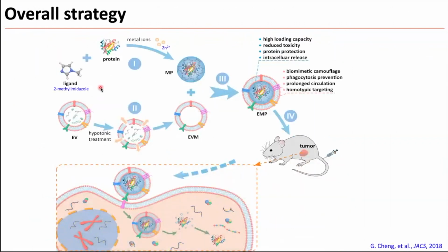Okay. So here's the slide of the overall approach. What we do here is we use a relatively new nanoparticle construct, in this case, a metal organic framework. You can see this nanoparticle synthesis is a self-assembly between a metal ion, in this case zinc, and a small organic ligand. And then we found it's possible to include proteins into this self-assembly process. So the protein is not on the surface of the particle, but really inside the particle. Because of this, we can significantly increase the loading capacity, and we can minimize the use of this ligand and metal ion so that we can reduce the systemic toxicity.